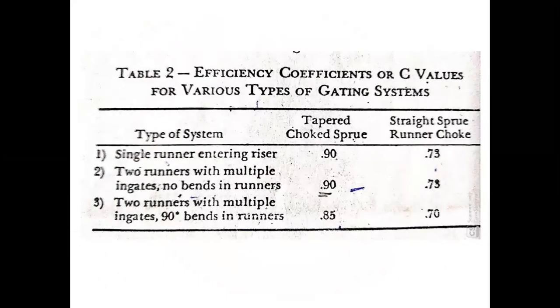Because choke area and pouring time depend on it. This is the efficiency coefficient of various types of gating systems. First is a single runner entering the riser. The second is two runners with multiple in-gates and no bend in runners. Then the third is two runners with multiple in-gates and a 90-degree bend in runners. Accordingly, 0.9, 0.9 and 0.85. This is the efficiency coefficient of the metal travel from the sprue to the casting's last point. This is also important.